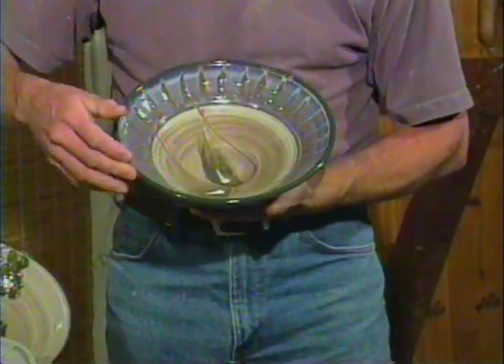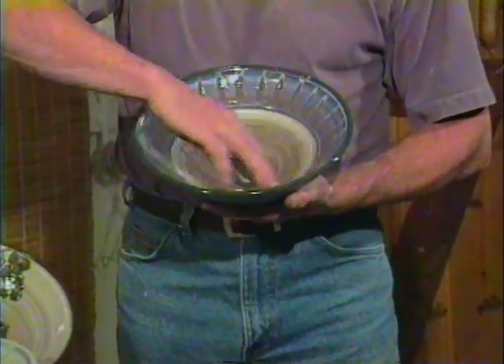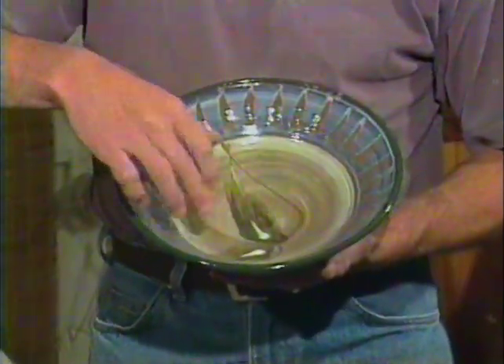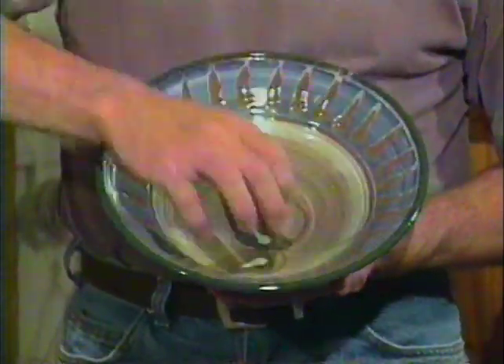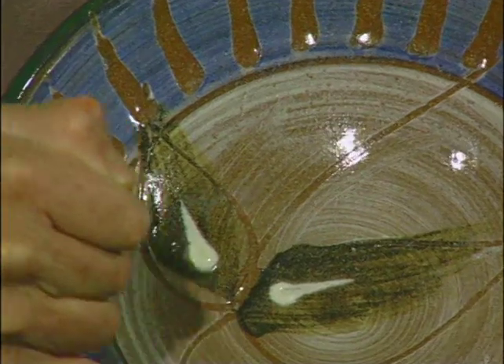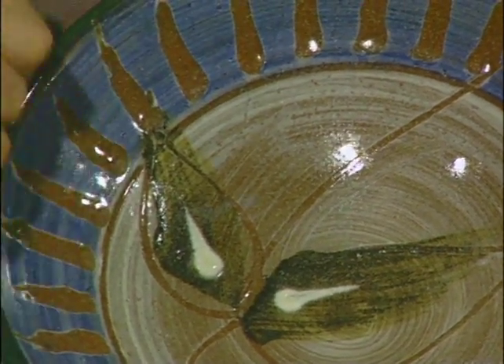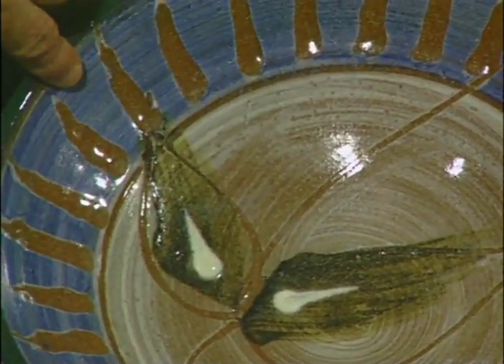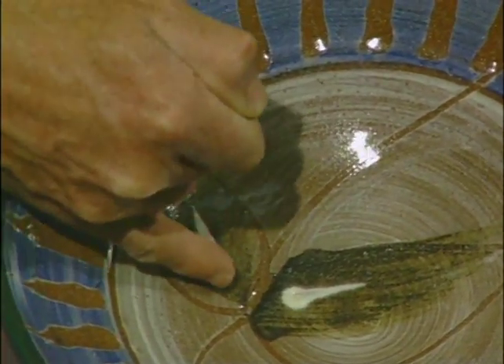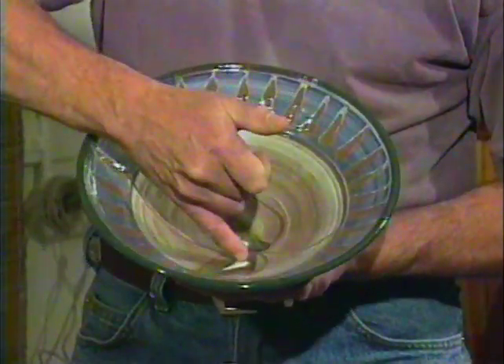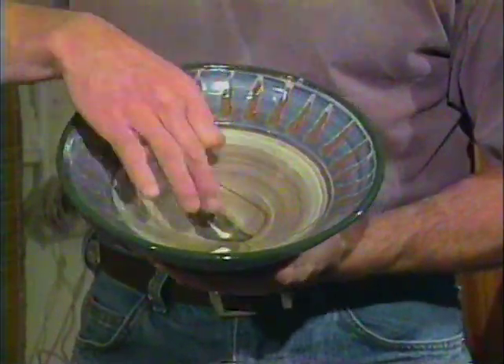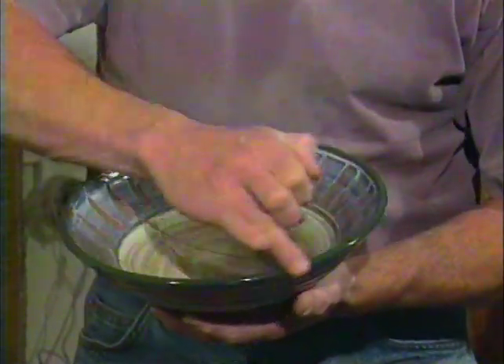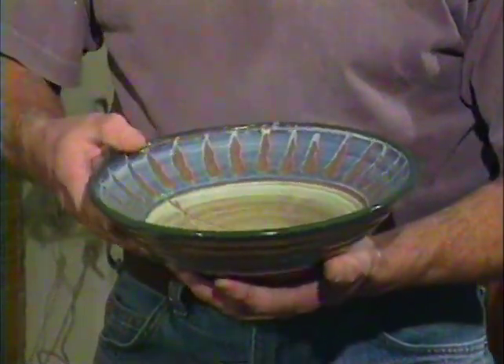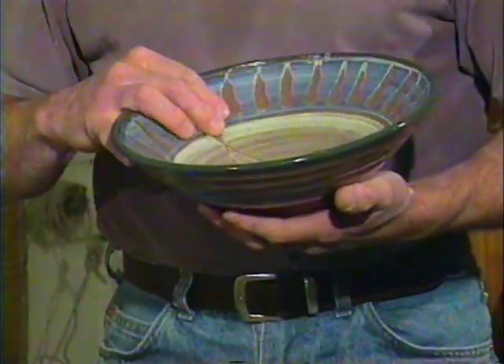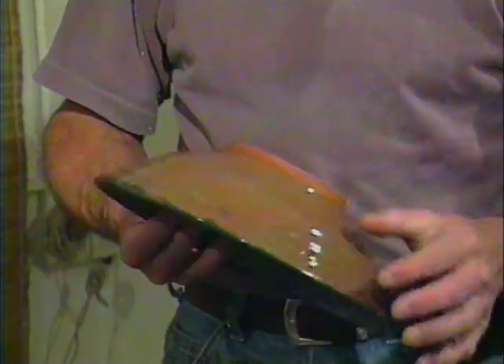In a piece such as this, I've initially covered the whole thing with a white slip broad brush, and then done the rim with a blue slip, incised through that with a loop tool, drawn the pattern with a stick, iron bearing slip, and then lastly a dollop of the white slip quite thickly applied, and around the rim here some of the green slip. The whole thing then dipped into the clear gloss glaze. There you see the original terracotta with no slip on it.